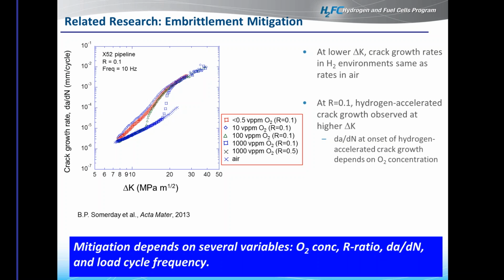So we also took the 1,000 ppm oxygen, and we tested it at a little bit more conservative R ratio of 0.5. And what we saw is that the data looks very similar to what it is in air. And so really what this shows is that very small amounts of oxygen impurities can help really mitigate the effect of hydrogen-accelerated fatigue crack growth. And it depends on a lot of variables, but some I've identified at the bottom: oxygen concentration, R ratio, fatigue crack growth rate, and the load cycle frequency.